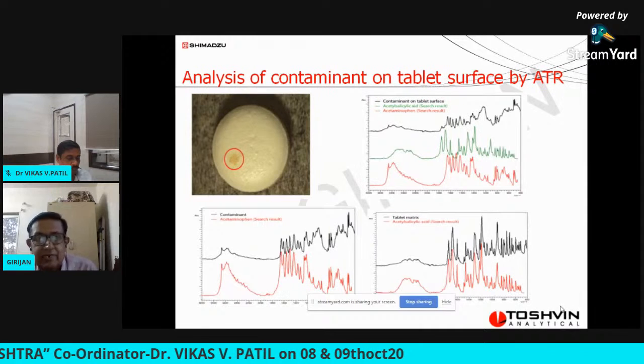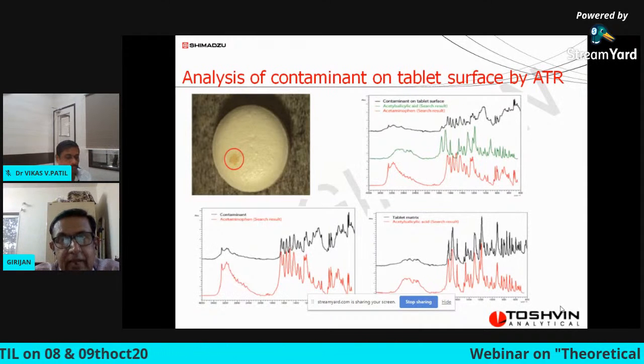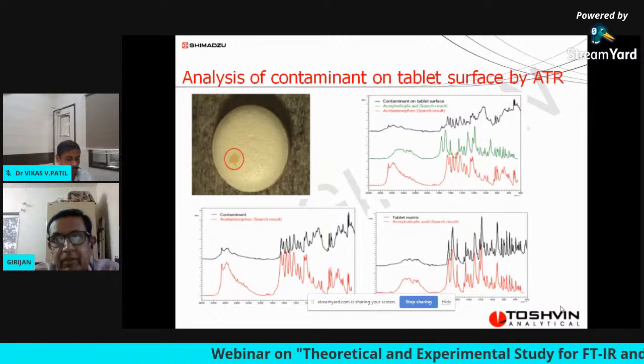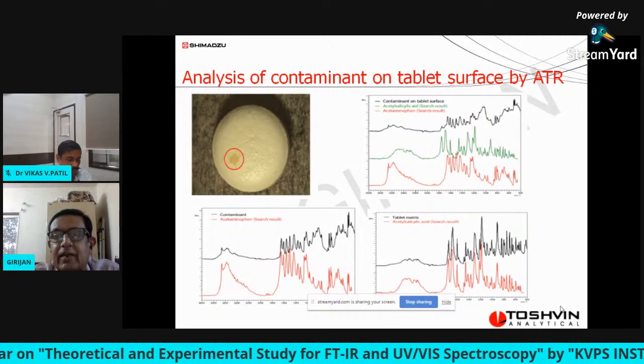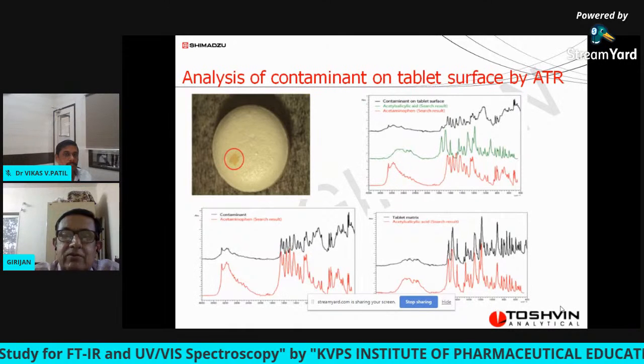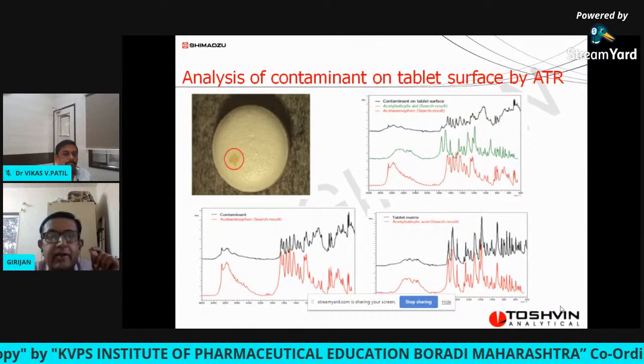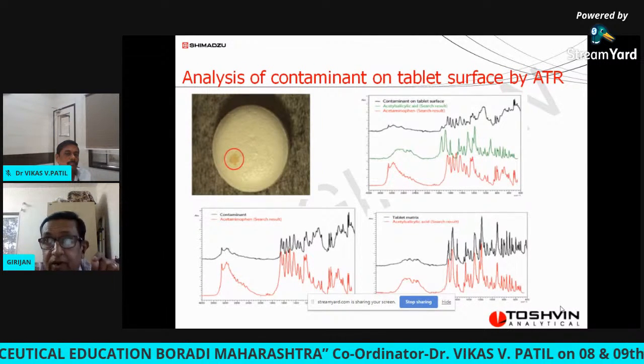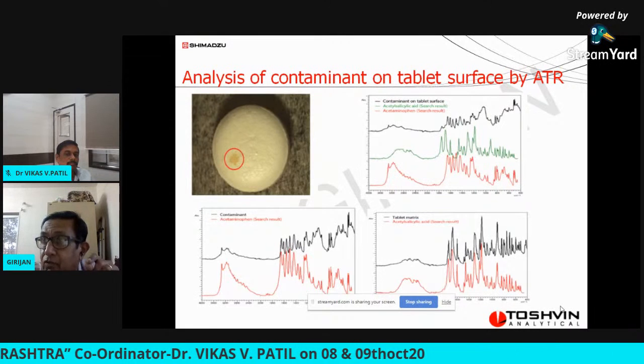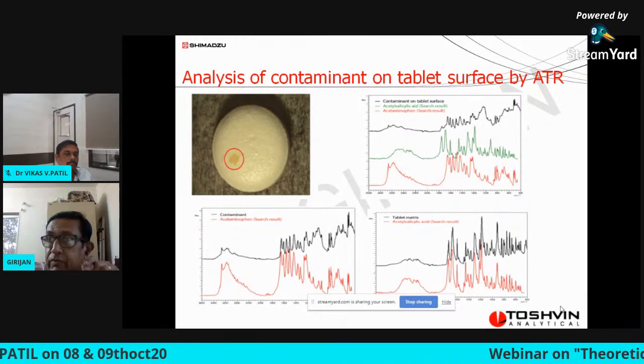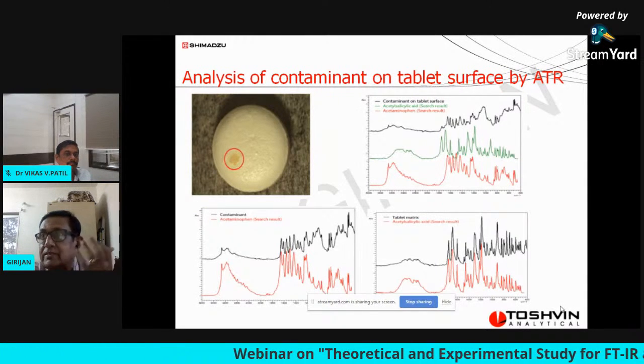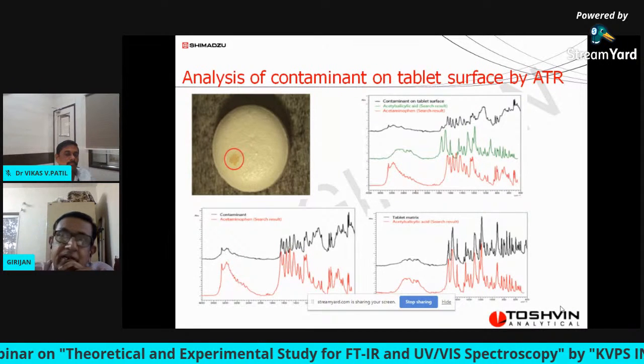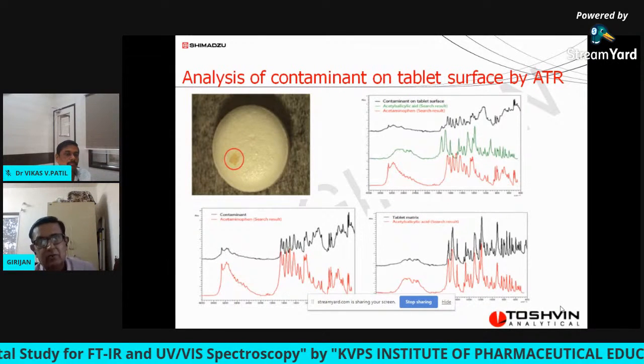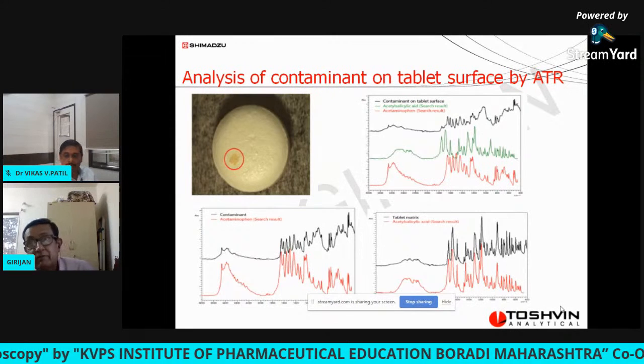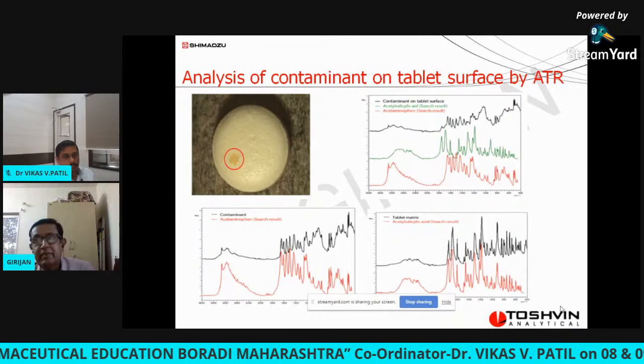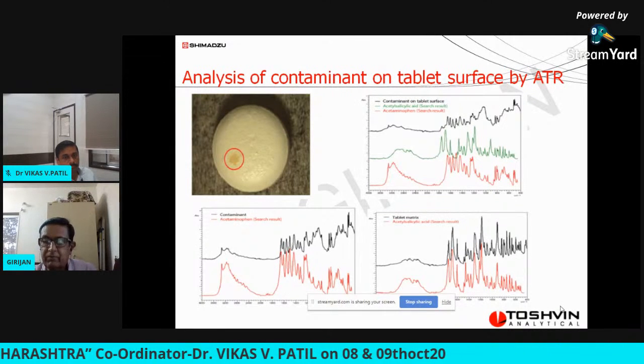Then we did one more experiment. From the normal part of the tablet, where there is no stain, the actual part, again we scraped a little material and recorded the spectrum, and that was identified as acetyl salicylic acid. So without any problem, we could identify the material. What was supposed to be a contaminant is not a contaminant. It's actually one of the materials in the tablet formulation itself. Maybe because of improper mixing, segregation has come on the surface. It is nothing but acetaminophen. It is not an external impurity. It is a very easy analysis. It's an analysis of contaminant on tablet surface by ATR. So we are confirming whether it is an external contaminant or an internal material. It was found to be an internal material. So that's confirmed. Very, very easy analysis.